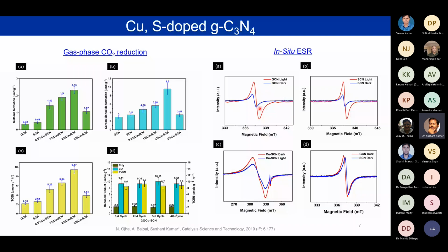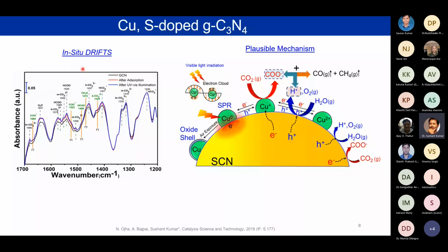Now, these are the in situ DRIFTS. What we do is pass the CO2 and H2O, we irradiate, and then we look at the DRIFT results, the IR results, and we see the new peaks that are forming. Though here you don't see very clear differences, when we do the second order IR derivative, we can see the spectral changes in much more detail, where the COO minus shows that the CO2 accepts the electron from the surface of the photocatalyst and transforms to COO minus. Now this COO minus becomes a very active intermediate, and then it starts reacting with the H2O, and it forms different species, which is shown here. I'm not going into the detail, but there are some reaction steps that have to happen.